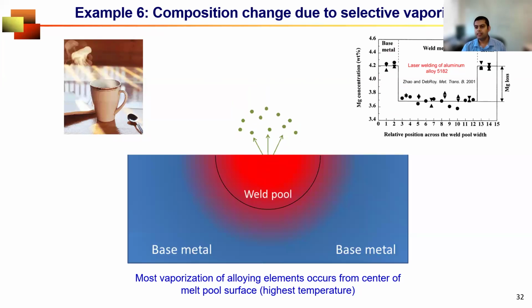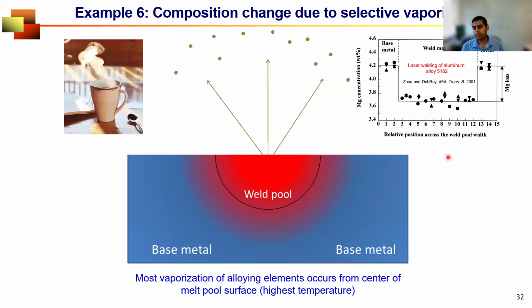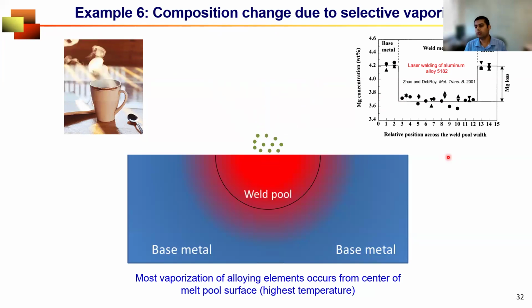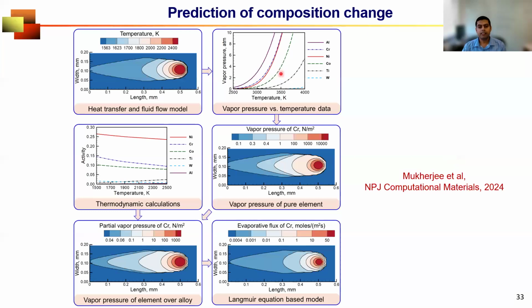For example, you see, this is an example of welding aluminum alloy, 5000 series. Magnesium is one of the prominent alloying elements for 5000 series aluminum alloy. And because of evaporation, there is a depletion of magnesium concentration. What does it do? It not only changes the composition, but it also changes the microstructure and mechanical properties. And if you are talking about stainless steels, it also affects the corrosion resistance. So all important properties that are related to serviceability, reliability, and performance are affected by this. So this paper just became available online yesterday in NPJ Computational Materials.